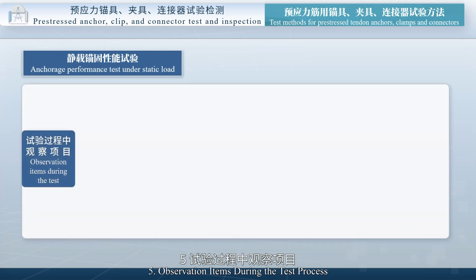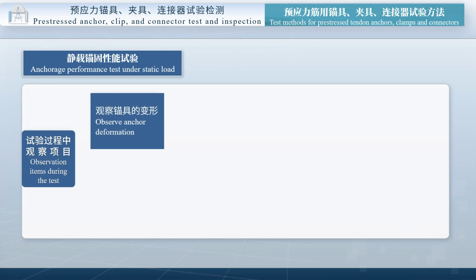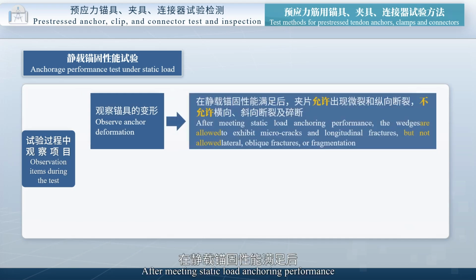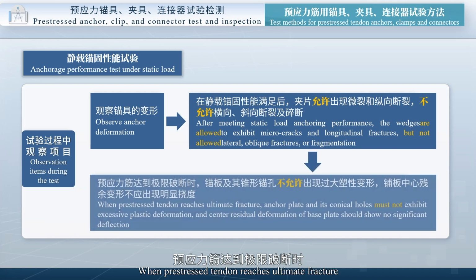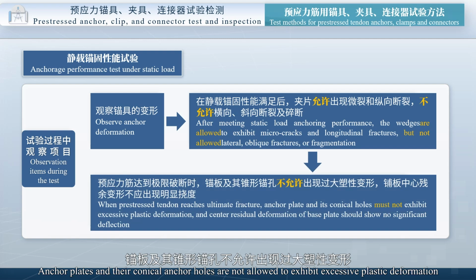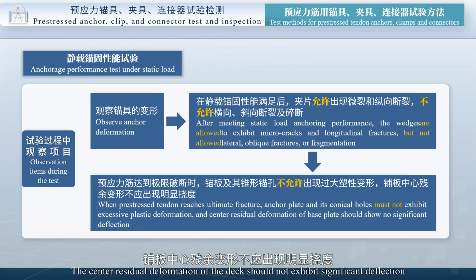Fifth, observation items during the test process. Observe anchor deformation and judge whether static load anchoring performance is met. Micro cracks and longitudinal fractures are allowed in clamps. Transverse, oblique fractures and shattering are not allowed. When the pre-stressed tendon reaches ultimate fracture, anchor plates and their conical anchor holes are not allowed to exhibit excessive plastic deformation. The center residual deformation of the plate should not exhibit significant deflection.